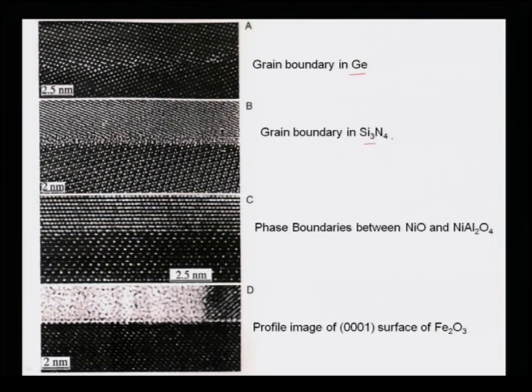You can see that the grain boundary of Si3N4, silicon nitride, has an amorphous layer of very small thickness, about 0.5 nanometer. And then the phase boundary between NiO and NiAl2O4, nickel aluminate, which is spinel, is very flat and very sharp. The last one, D, is basically a profile image along the 0001 surface of hematite, where you can see the black and white dots of iron.